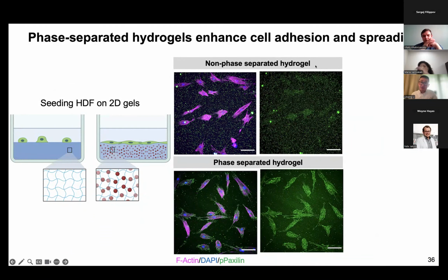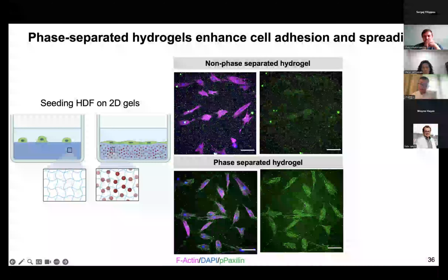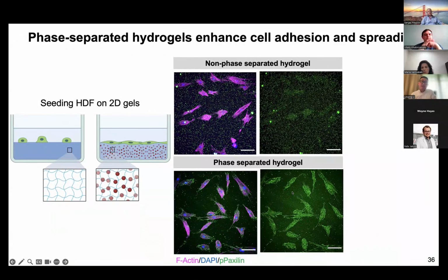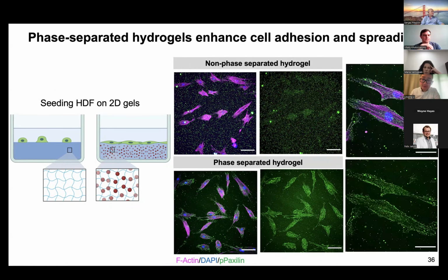So in the non-phase separated gels, which have higher modulus, we see less cell area and less defined focal adhesions. Here you see the cells actually have smaller area compared with the phase separated hydrogels. In the phase separated gels, we use phospho-paxillin to show the focal adhesions, and you can see that in the phase separated hydrogels the cells form really well-defined punctate focal adhesions. If you zoom in, you can see these on the edge and over the protrusions at the front and the end of the cell.